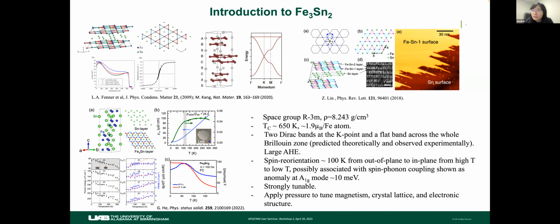All right, so before we get started, I want to first give you some introduction of this specific compound. It's called the Kagome magnetic metal. In this compound, there are two iron Kagome layers separated by a thin honeycomb spacing layer. When you cool down from very high temperature below 650 Kelvin, the system becomes ferromagnetically ordered with a canted moment. The magnetic moment in this case is 1.9 μB per iron atom.